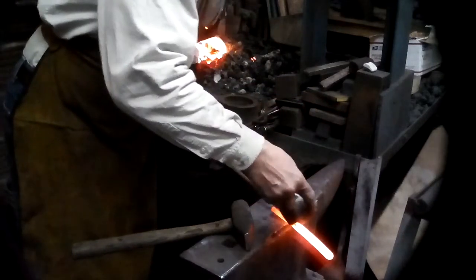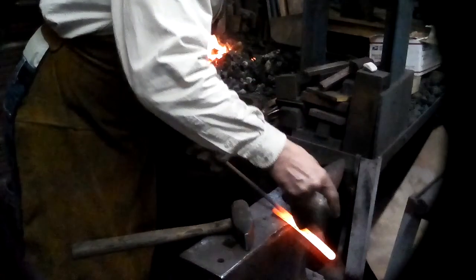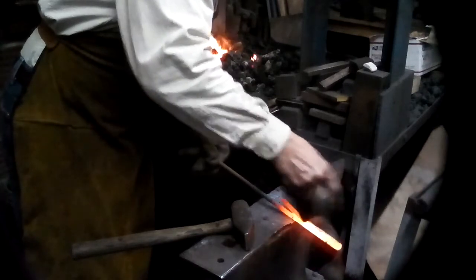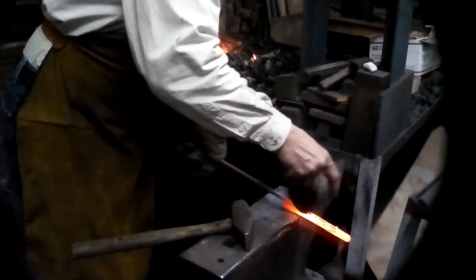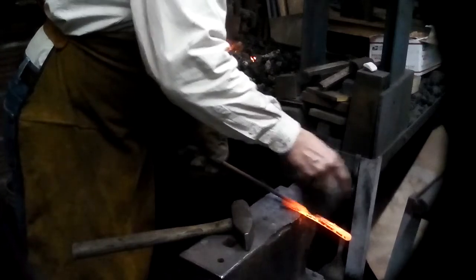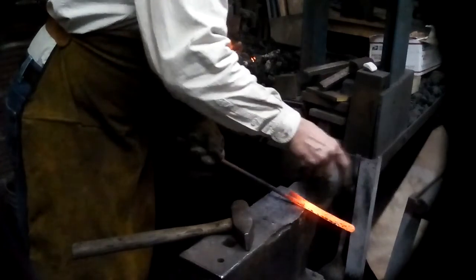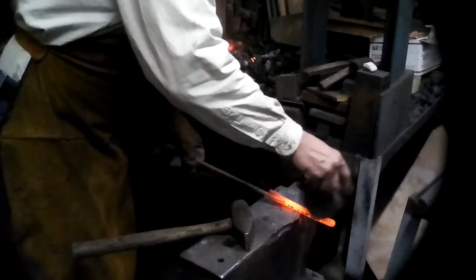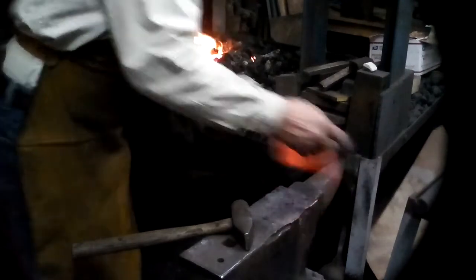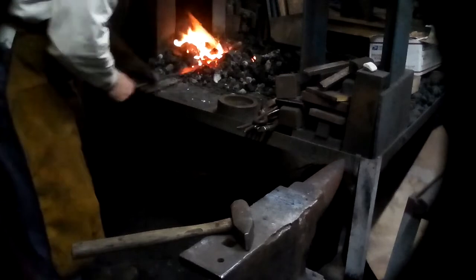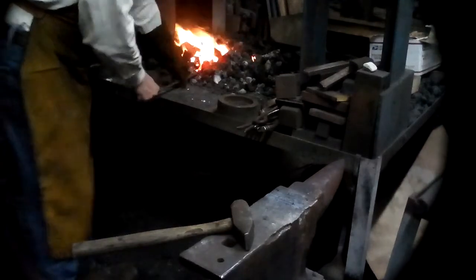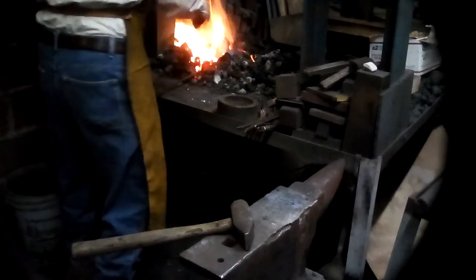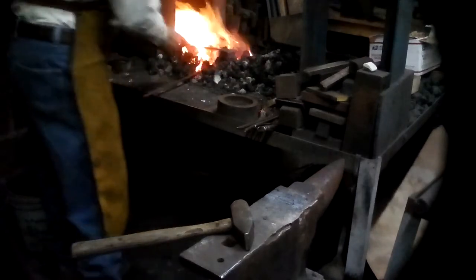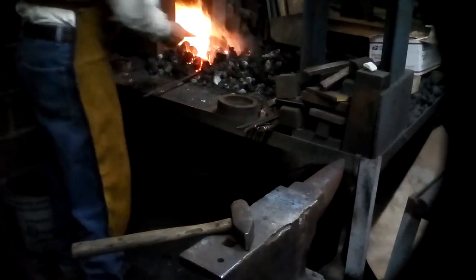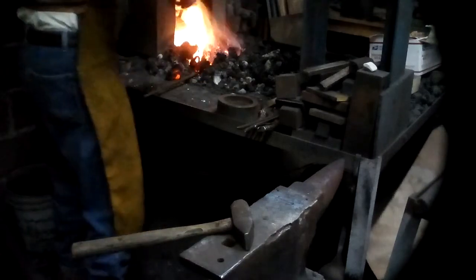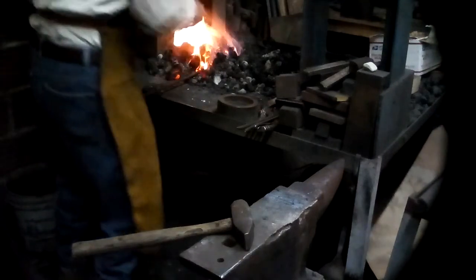I'm going to do what's called an insurance weld. This will also give you a second chance to see what a forge weld looks like. Because there's nothing that says, as long as you've got enough thickness and you have not melted the metal, you can always go back and weld it again. And depending, it's okay to take an insurance weld. You'd rather have two modest welding heats than one heat that's way too hot.